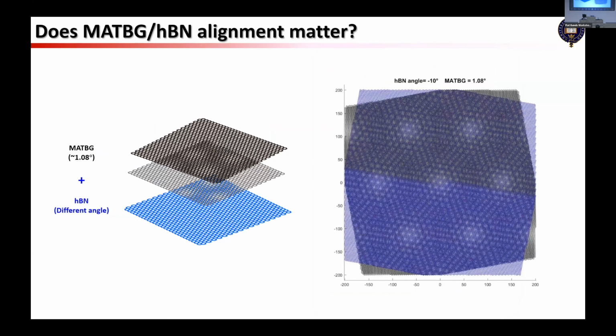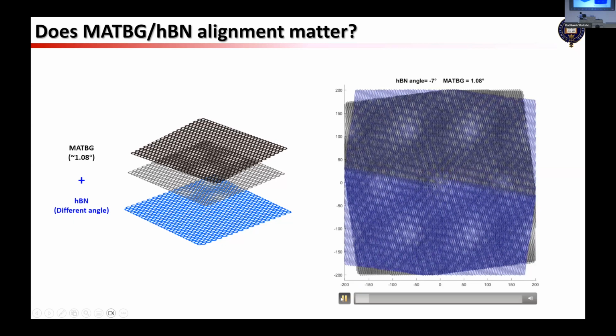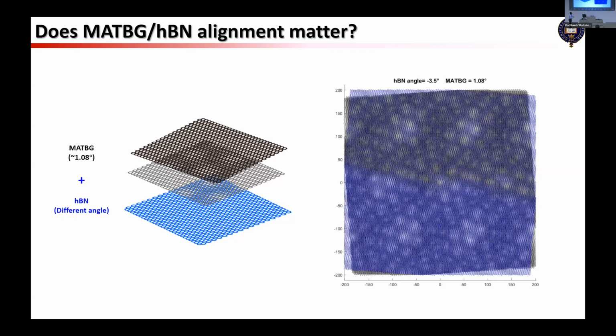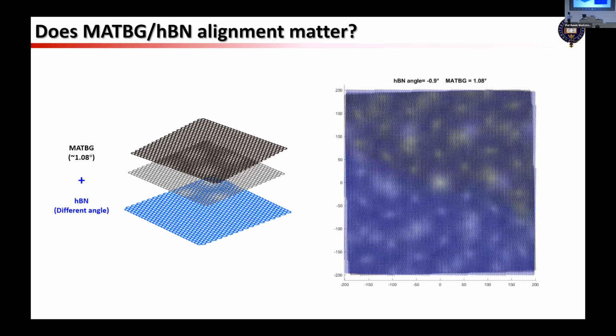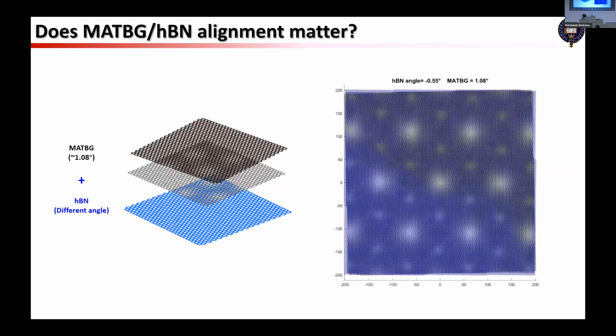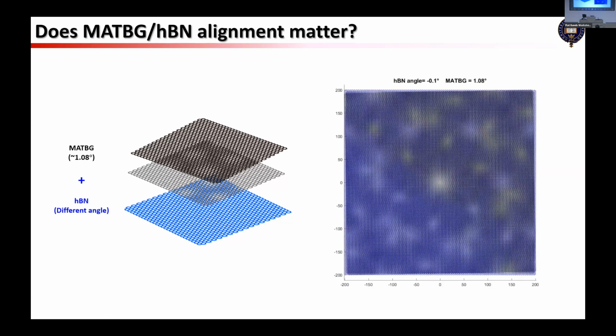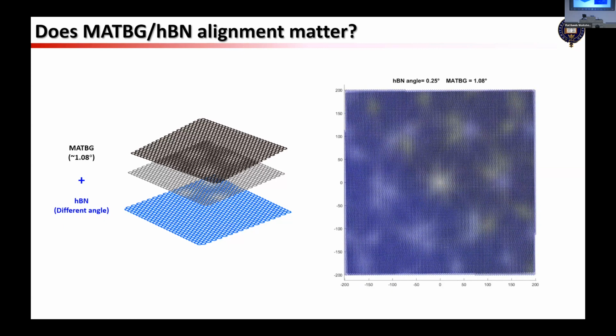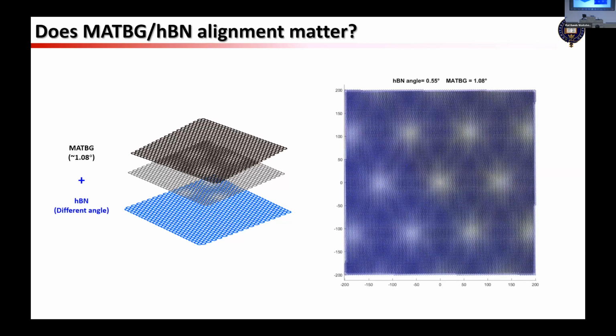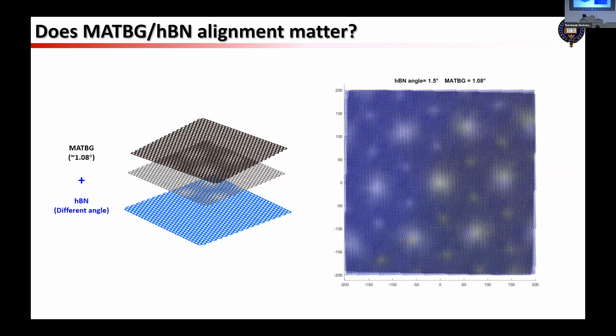If we just take a quick look, you see that with a different twist angle between the HBN and the MATBG, the moire can also change. This 6-point pattern was the original moire from the MATBG, but when the MATBG has a different twist angle with respect to HBN, the moire can change the whole landscape a lot, from a high frequency modulation to a very low frequency modulation, with a period almost identical to MATBG.